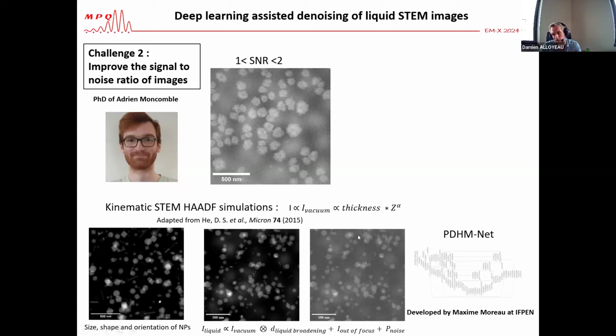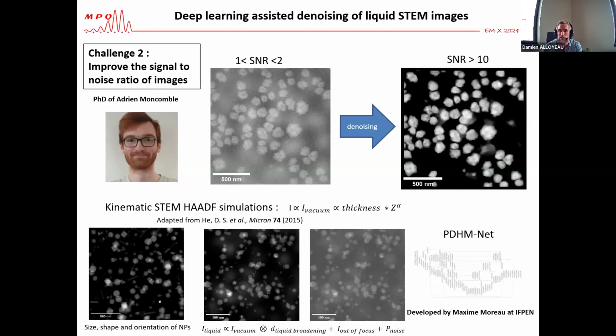And you see that the images that we simulate here are very similar to our experimental images. And we can give the neural network these noiseless images, which allows the network to reconstruct extremely well-defined images of our nanoparticles with a signal-to-noise ratio up to 10. So now that provides a lot of new possibilities.